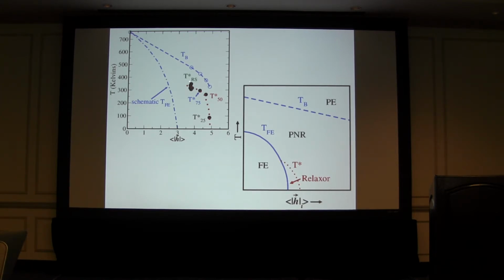5 random site calculations here. And the spread that you can see is akin to a finite size analysis. I can't make an infinite box and sample all of the possible configurations, but I can sample some of them and they all give pretty much the same results. And you can see we're getting essentially the same prototype phase diagram, with this curve coming over towards what I've schematically drawn in as the ferroelectric transition.